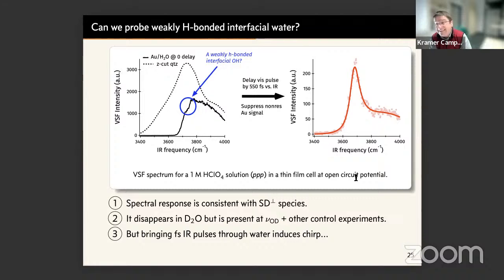So this feature is now consistent with what we would expect from a weakly hydrogen bonded water molecule, a weakly hydrogen bonded OH stretch. One sees similar spectral features for water at hydrophobic interfaces or water at the air-water interface. Of course, you need to do control experiments, so it disappears in D2O but is present at OD stretch frequencies, to convince yourself that this is at least plausibly an interfacial free OH.